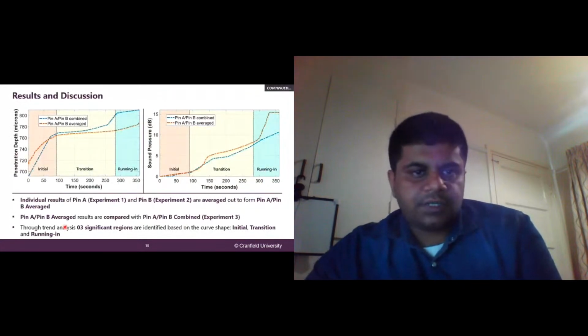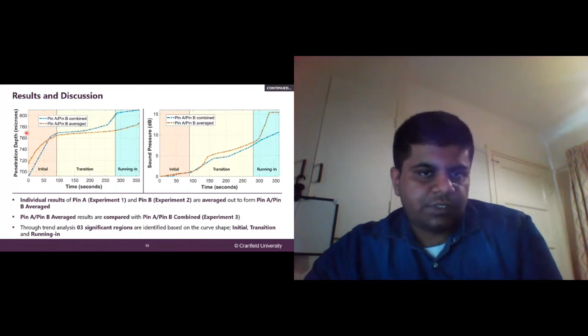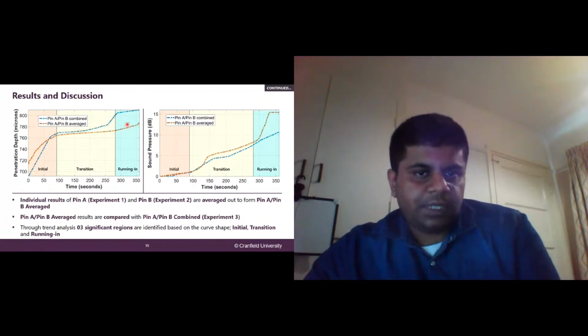So these are the results. As you can see, individual results of pin A experiment 1 and pin B experiment 2 are averaged out to form pin AB averaged. So this particular orange line is when you take the average of experiment 1 and experiment 2 and plot it on this graph, which is penetration depth against time. And pin AB are combined results which follow a very similar trend to the one shown before. They're in good correlation. If you even see the values, this is only a 20 micron difference more or less at this point.